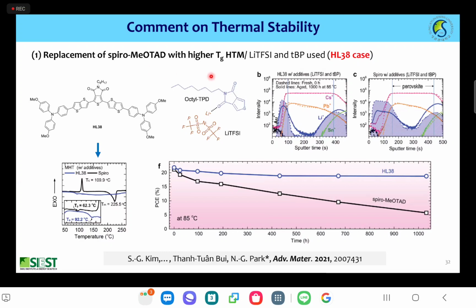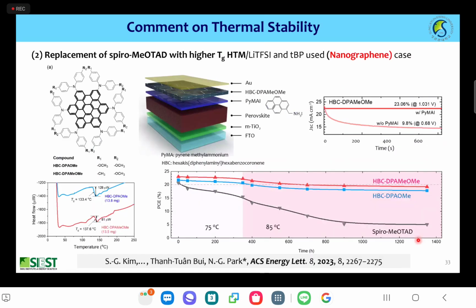Then we have to synthesize the HL38. This molecular structure looks like this one. And this shows a higher glass transition temperature, even in the presence of the lithium TFSI and the TBP additive. And then we observe very good thermal stability at 85 degrees C for the 1,000 hour aging test.